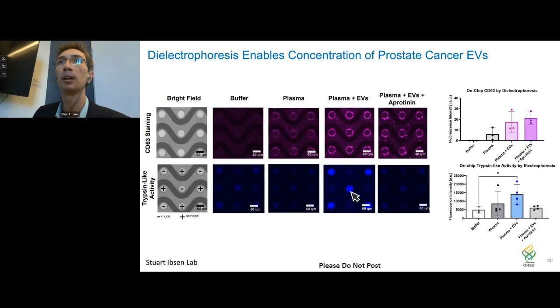When we use a protease inhibitor, here aprotinin, we can actually stop trypsin activity almost entirely, and we see a great reduction in this signal. So we know that the signal we're seeing here is truly from protease activity. And proteases are really important because in order for the tumor to expand, it has to have protease activity that it's overexpressing. And this is a really powerful biomarker to add to our panel.